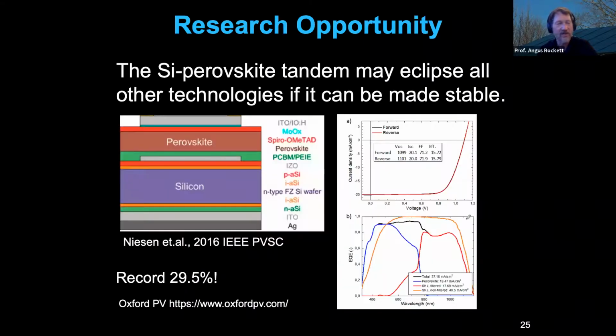Well, this has been done with silicon in conjunction with these so-called perovskite materials that I'll mention a little more about. And so this particular example was reported in 2016. The efficiency of this device is not that good. It's about 16% in a tandem. The remarkable thing is that recently there was a record device produced of 29.5%. So a couple of percent more efficient than silicon, one of the best tandem device performances around. And this is a silicon perovskite combination.